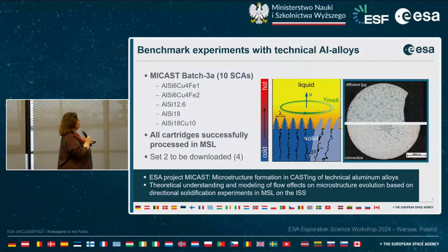As I said before, the top part was solidified under pure diffusive mass transport conditions, whereas the lower part was solidified when the rotating magnetic field was switched on. So what you see, I hope you can see it, is that in principle you look on top of these dendrites, you see the cross-sections of the dendrite arms lying on a more or less defined network in a matrix, let me say.